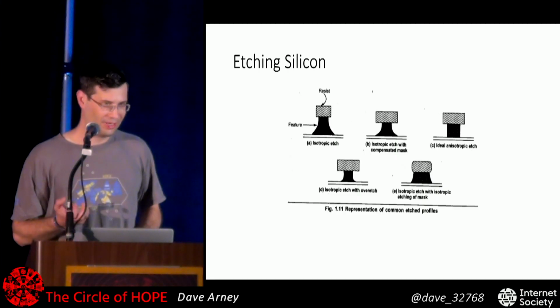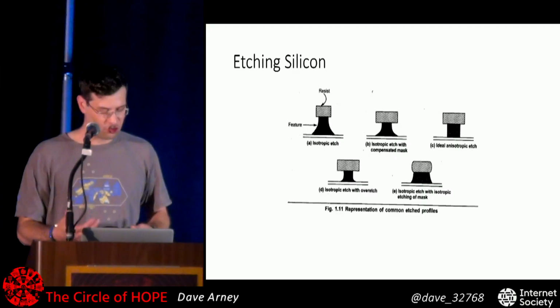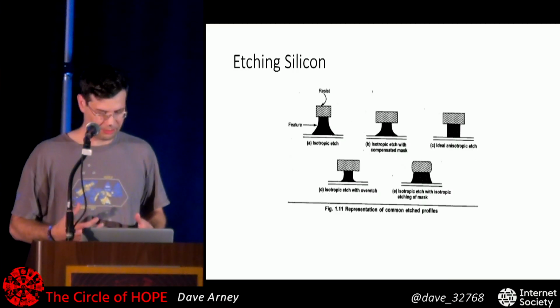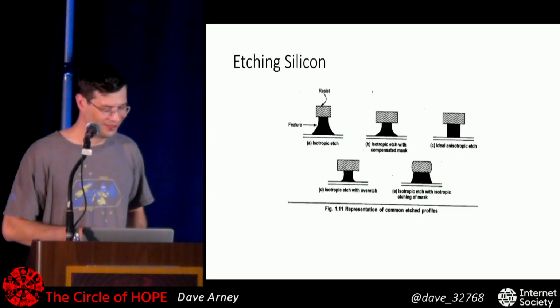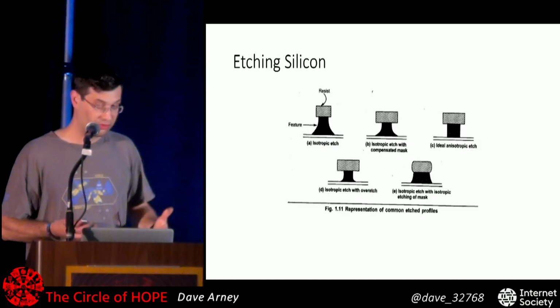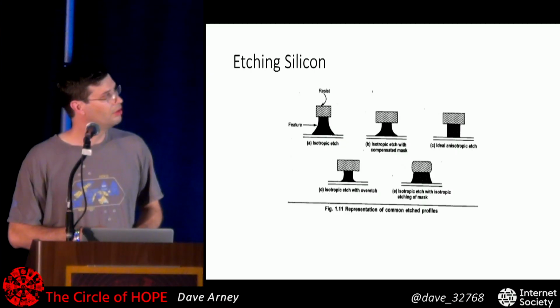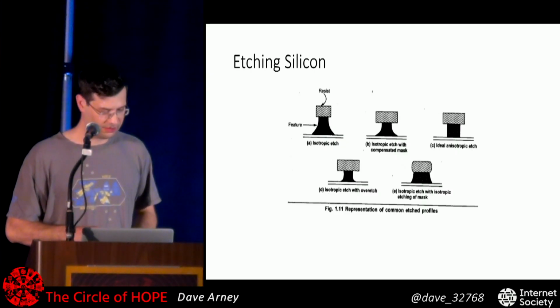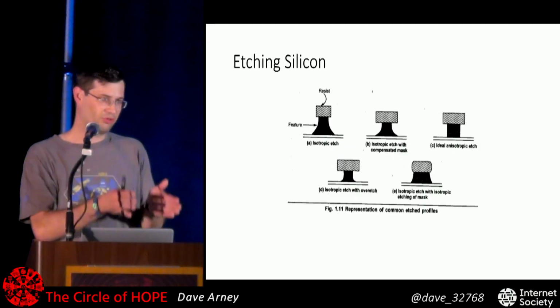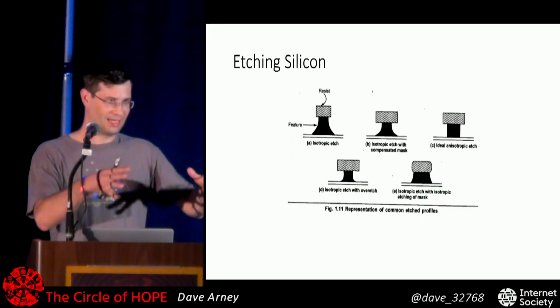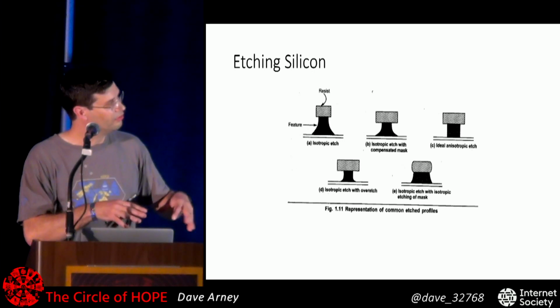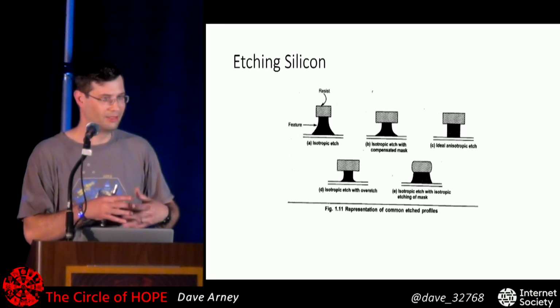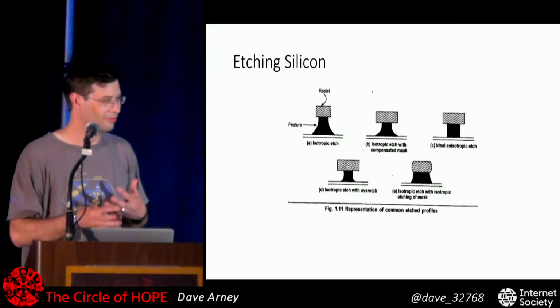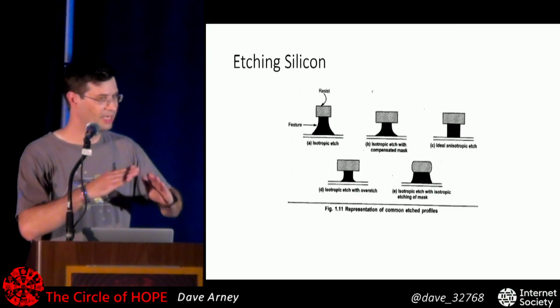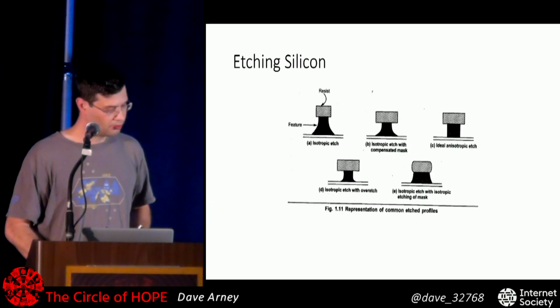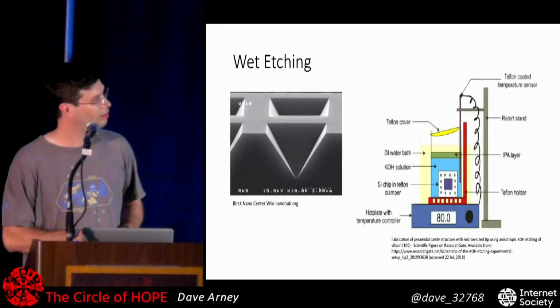Once you've got the pattern written on your mask, you then need to etch away the silicon. And this is where we start to get into some of the more industrial processes and equipment. There's two basic ways of etching. If you use a chemical etch with silicon, you end up with something like this, which is called an isotropic etch. You don't get straight lines up and down because the chemical's kind of attacking from the sides, and the silicon crystal is oriented in such a way that you end up with, depending on the exact kind of silicon, usually around a 55-degree angle, slopes to your edges. So you end up with something that looks like that.